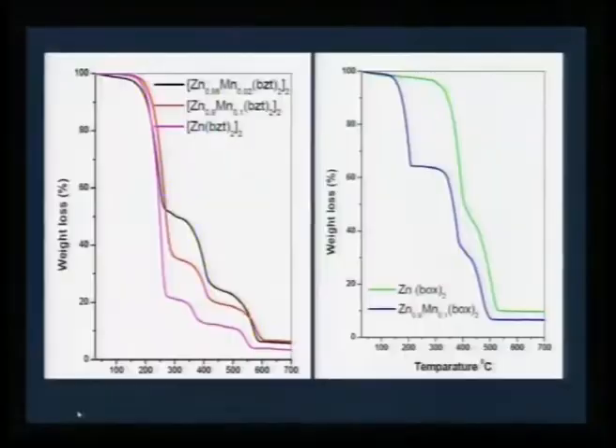So, for the first time we are showing that if you take a precursor route, it is possible to carefully dope manganese in the zinc site without any phase segregation. As a result, we can stabilize a dilute magnetic semiconducting phase, and this is one of the very novel results that would take this wet chemistry route a long way.